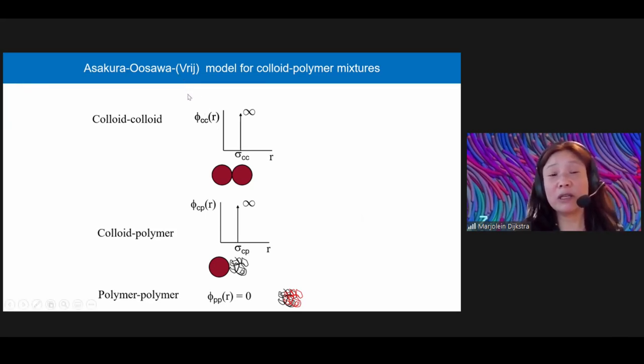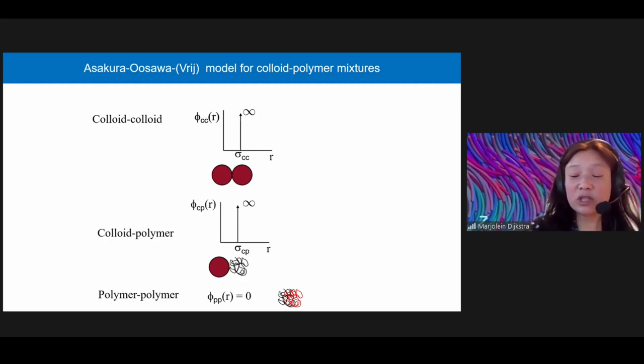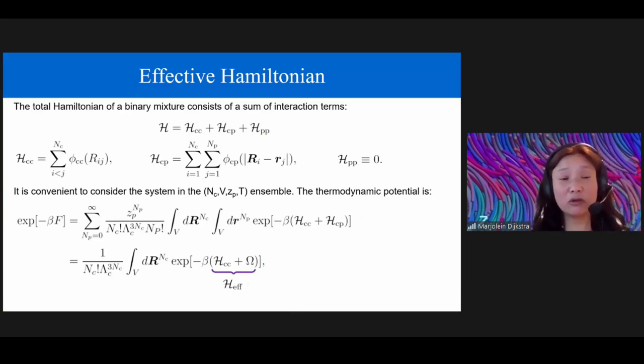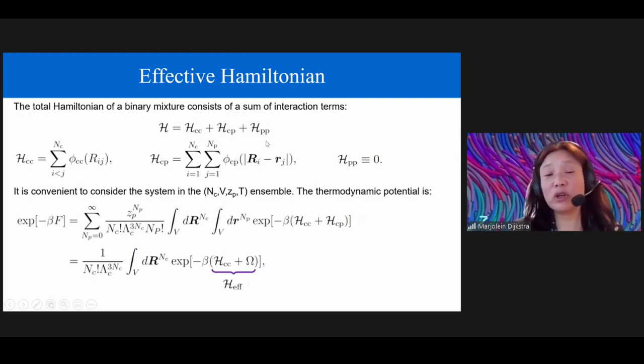And so the simplest model that captures this depletion effect was introduced by Asakura and Oosawa in 1954, and Vrij in 1976. He treated the colloidal particles as just hard spheres. The colloid-polymer interaction is also treated as a hard-sphere-like potential, but the polymer-polymer interactions are treated as ideal particles because the polymers can interpenetrate each other. And so for this very simple system, one can write down the total Hamiltonian. This consists of a colloid-colloid interaction term, a colloid-polymer, and a polymer-polymer interaction term. These are just a sum of all the pair interactions.